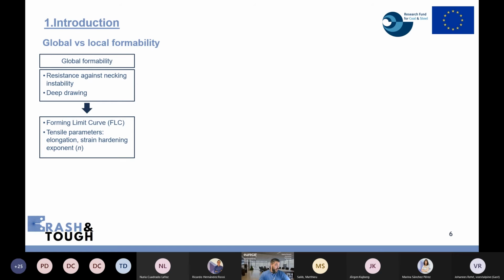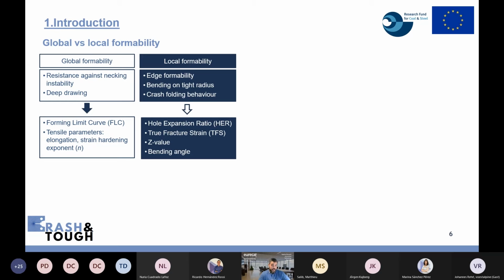The global formability is the traditional definition of formability, which is the resistance against the necking instability, and is well represented by conventional forming operations like deep drawing, and is well represented also by forming limit curves or conventional tensile parameters based on the elongation through uniform strain, for example, or the strain hardening exponent. Then, on the other hand, we have the local formability, which is more related to the fracture resistance of the material. Some examples of local formability operation modes are edge formability, or bending on tight radius, or the crash folding behavior.